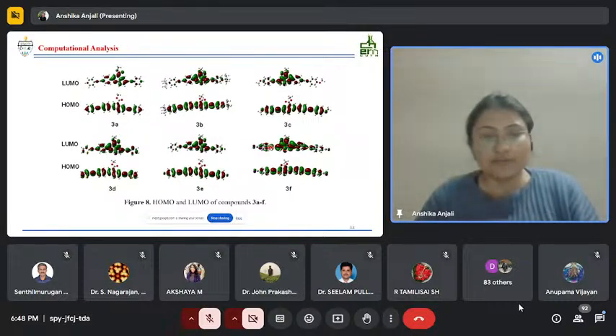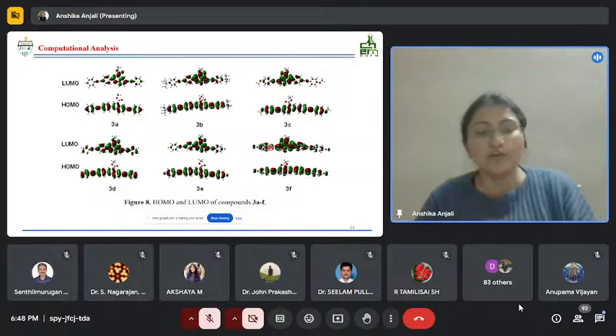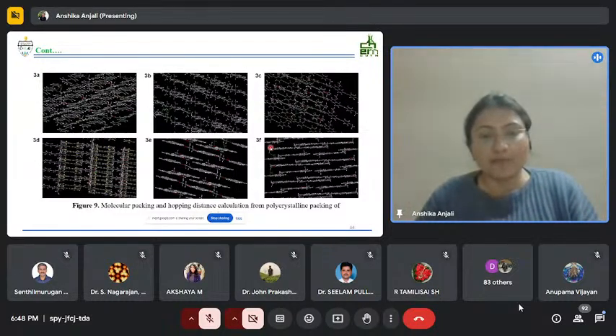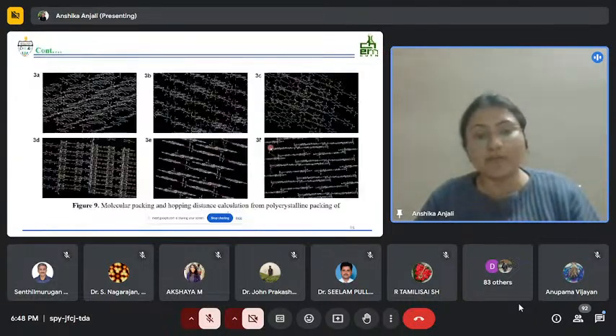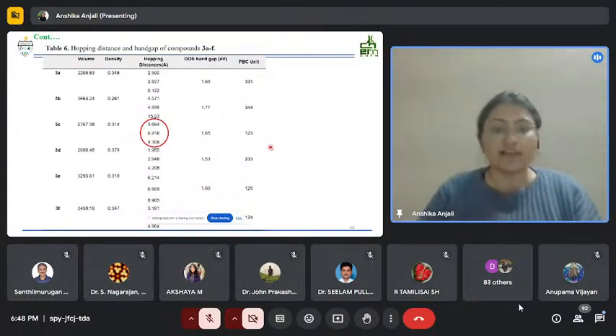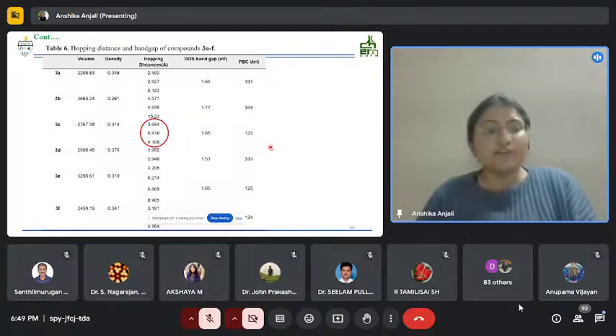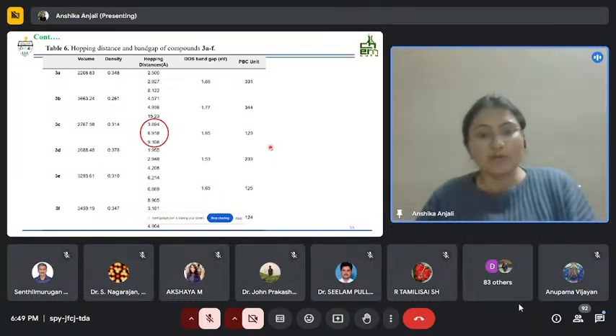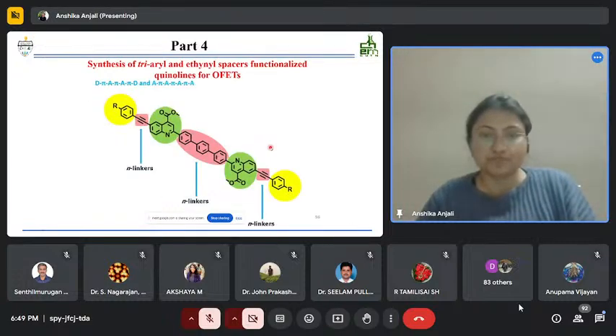Their electron density distribution curve suggests that for these compounds, the HOMO and LUMO energy levels were extensively delocalized. Their molecular packing was also studied, and from the molecular packing, we calculated the hopping distance values, which favor compound 3C, with 4-methoxyphenyl at the end terminal. They have lower hopping distance values.